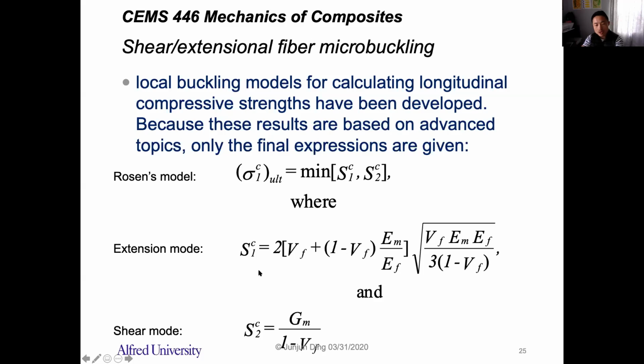So for this extension mode, it's calculated based on the volume fraction of fiber, Young's modulus of the matrix and fiber, right? And for the shear mode, it's calculated based on the shear modulus of the matrix and volume fraction of the matrix. Okay, so you want to compare if this composite will fail in the shear mode or the extension mode. If this is shear mode, the stress is smaller, that means the composite will fail in this way, right? Otherwise, it will fail in the extension mode.